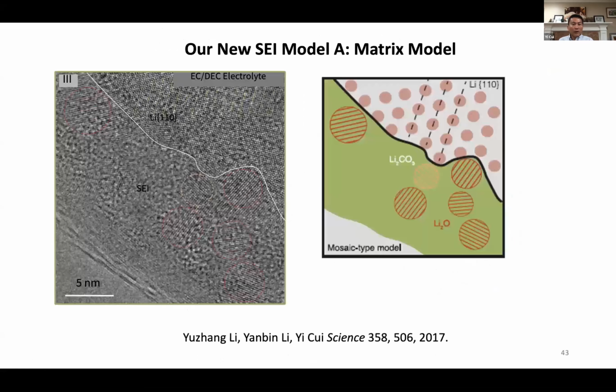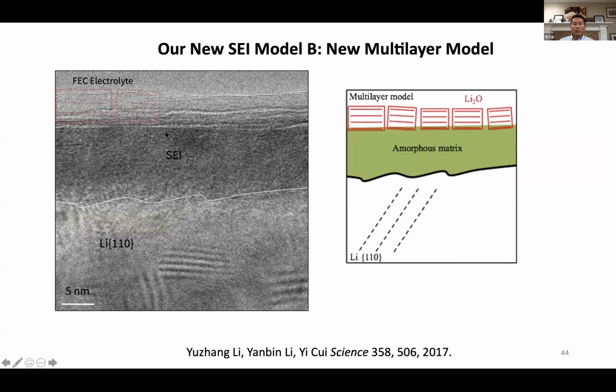And we used cryo-EM to resolve the SEI structure down to atomic scale resolution. With 1 electrolyte, carbonate without fluorinated carbonate, we find out it's more like a mosaic model, right? It's actually more like a matrix. It's inorganic particles embedded into this organic matrix, about 20 nanometers thick. And as soon as you add in fluorinated carbonate such as FEC, it becomes a multi-layer, in this case bilayer model, with an amorphous layer, and then at the top is an inorganic coating, beautifully and uniformly. We could correlate the electrochemical performance with the SEI structure for the first time as well, and find out this multi-layer model is actually working so well, and you need a uniform SEI.